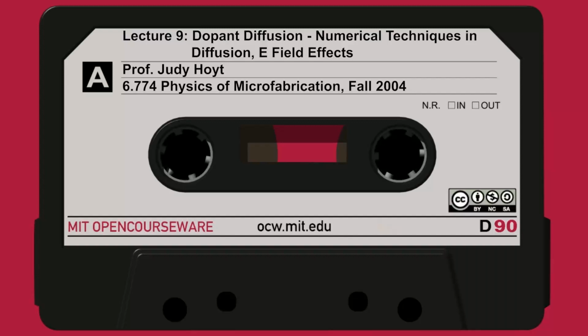Now the metallurgical junction is the point in depth where the chemical concentration of the diffused dopant in the diffused region equals the background concentration, Cb. I will do an example shortly where you can see how these curves are used. Each curve, a different color, is for a different background concentration. So this tells you that these 3 key parameters have a unique relationship among themselves for the case where the shape of the profile is known. In this case, it's Gaussian.